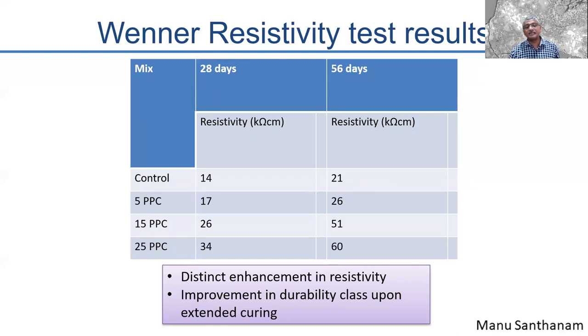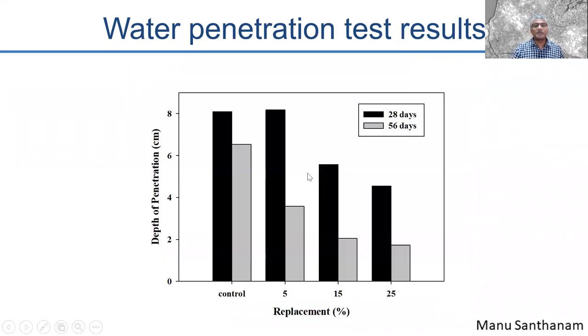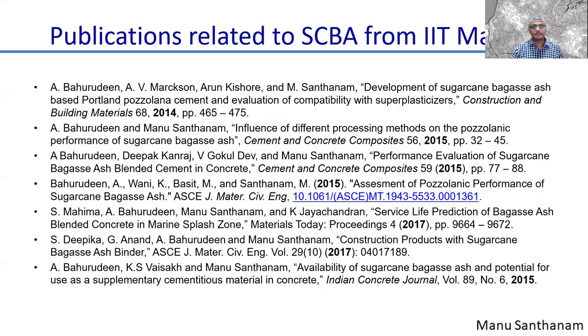So higher resistivity or lower conductivity means better concrete quality. Again, you can see very clearly that the resistivities of the blended cement concretes are definitely better as compared to control concrete. So all the durability results seem to point to the fact that your bagasse ash based concrete is superior to your ordinary Portland cement based systems. Again, water penetration depth, another positive result: you can clearly see that the penetration depth goes down as you increase the replacement level of the bagasse ash.